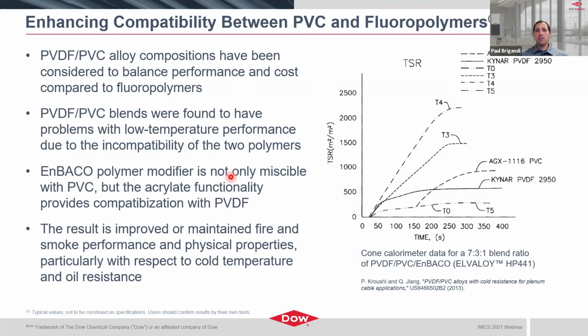In most cases, in this particular example, we're looking at polyvinylidene fluoride, PVDF, with PVC. One of the problems is with the low temperature performance. Basically, here we're showing incompatibility between the two polymers, so the PVC and the fluoropolymer.